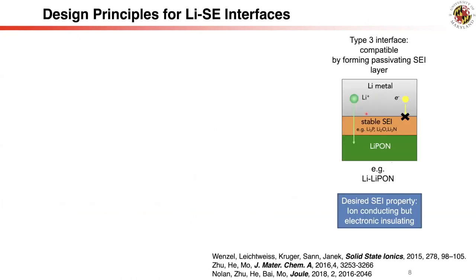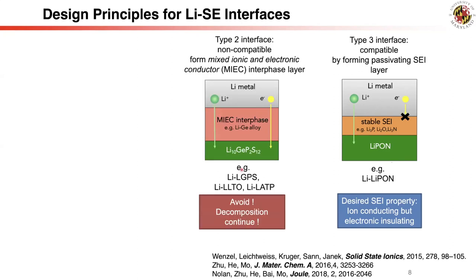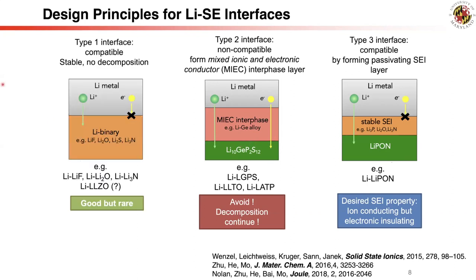Our understanding of lithium-solid electrolyte interfaces can be summarized into three types. Type three: lithium-LIPON interface forms a stable passivating SEI layer; the interface layer with good lithium-ion conduction and electronic insulation is critical. Type two: for lithium metal interfaces with LGPS and other materials, the reaction forms a mixed ion and electron conducting interface layer, which cannot passivate and leads to continued degradation. Type one: thermodynamic intrinsic stability between lithium metal and solid electrolyte exists, but not many materials have such stability. This classification provides guiding principles for lithium-solid electrolyte interface design.